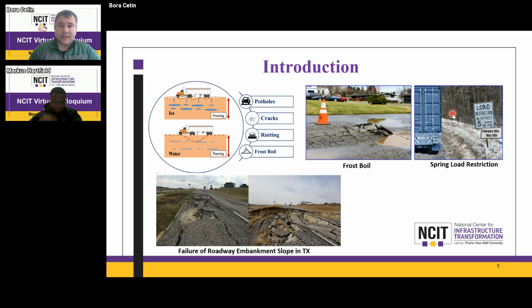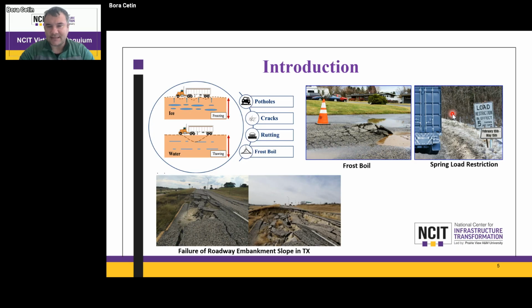Here are some examples of roadway failures that happened because of freezing and thawing or wetting and drying cycles. And you would be shocked to hear the results. The damage caused by expansive soils and frost susceptible soils subjected to wetting and drying cycles and freezing and thawing cycles, in budgetary terms, is 10 times higher than the damage caused by hurricanes, flooding events, and even earthquakes. So these are not sudden, crazy failures like we see in flooding events, earthquakes, or hurricanes and storms, but annually, the U.S. needs to deal with these two types of problems. So it's really a major problem.